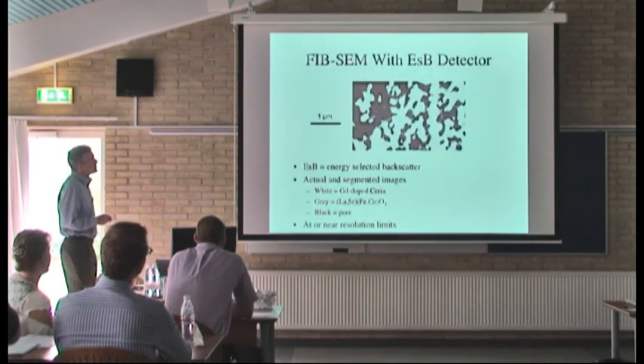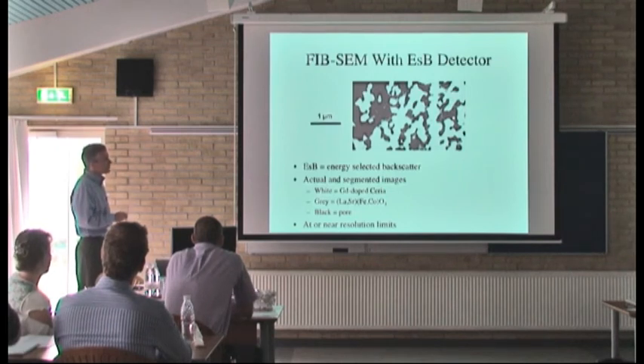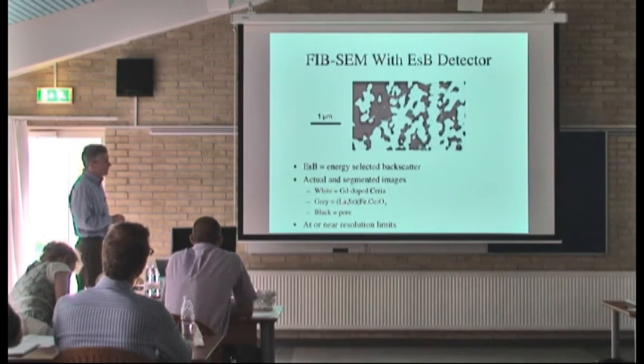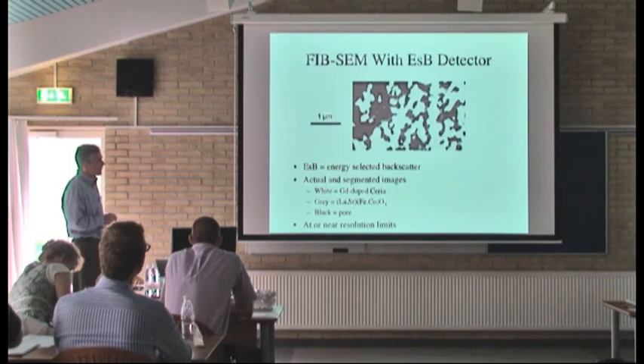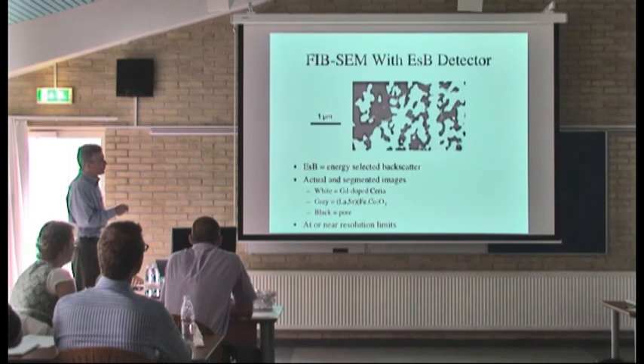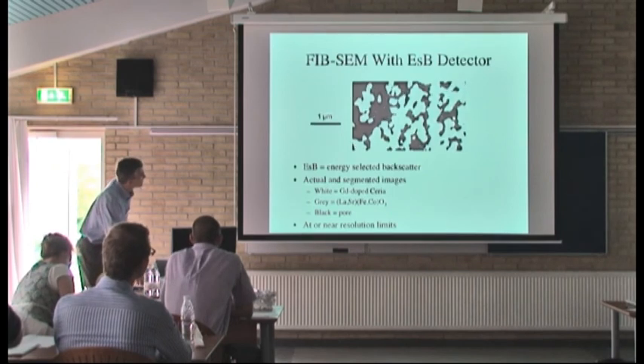We've been trying to push the limits of the FIB-SEM by doing measurements on infiltrated cathodes. In this example, we start with a porous backbone of gadolinium-doped ceria, visible in white, and then infiltrated lanthanum strontium cobalt oxide material in. Using the ESB detector, we can get some contrast between the infiltrated phase and the backbone phase. The challenge is that we're resolving particles that can be down to 50 nanometers, which is really pushing the resolution limits of the technique.